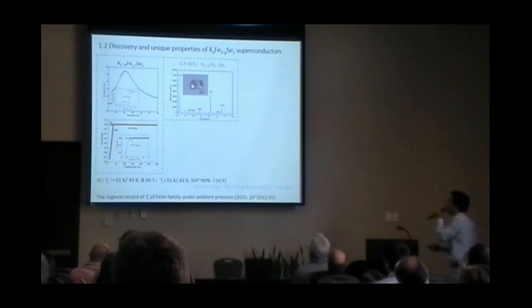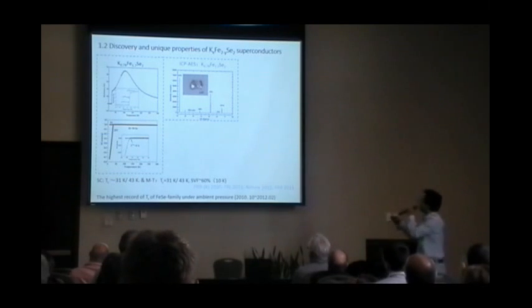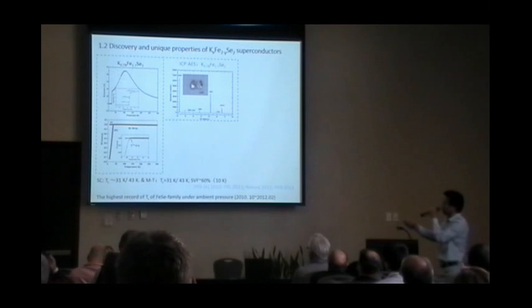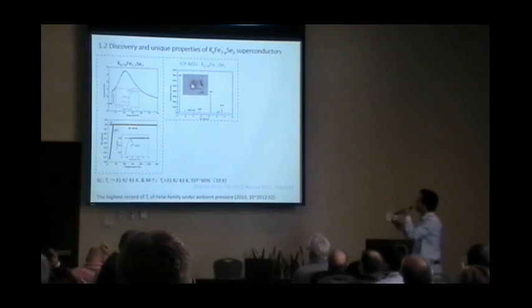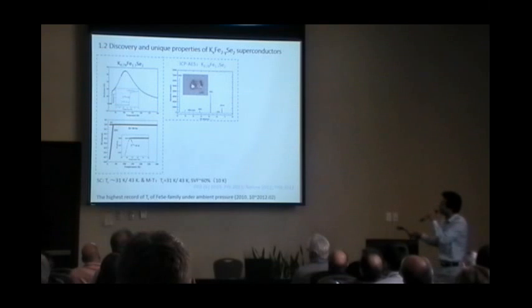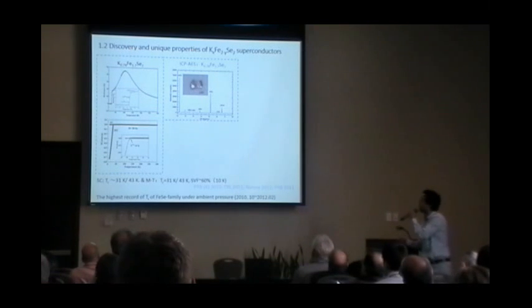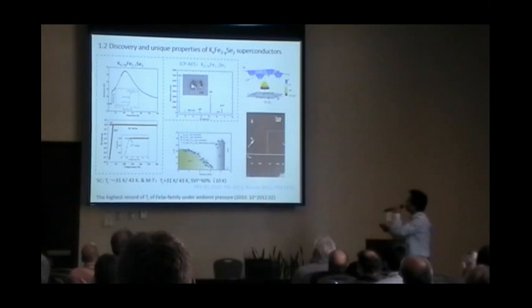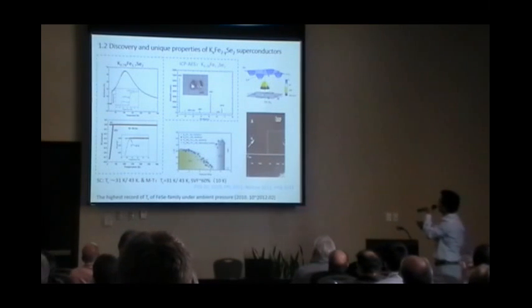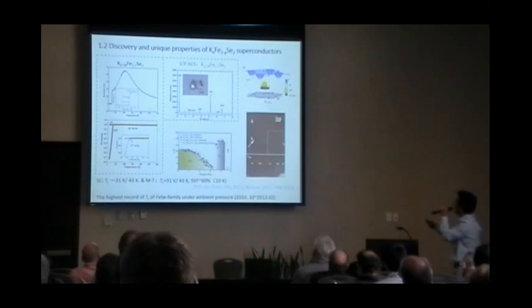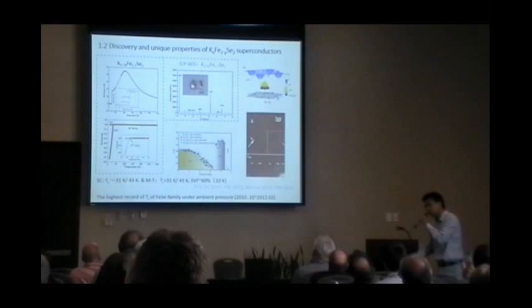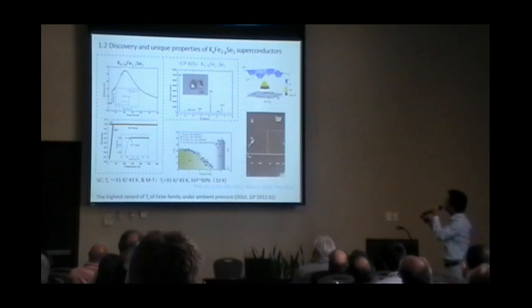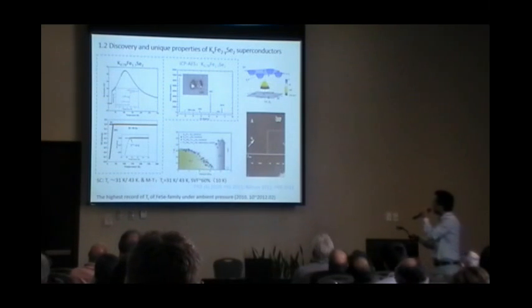In 2010, we did some work on this 11 system, and we used potassium to intercalate the system. We found that the TC increased from almost 8K to around 31K. We also grew single crystals, and after we grew them, we collaborated with another group and got this Fermi surface showing here. You can see there is no hole pocket at the gamma point. So it raises the question of why the TC is so high. There is no general conclusion about this.